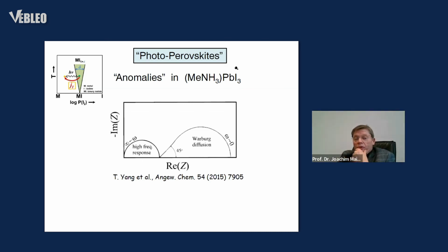Imagine you have such a material and you measure it with a DC current or AC, between 2 electrodes that naturally block the iodine ions. They block it. So what happens is you accumulate the iodine ions on one side, you deplete them on the other side, so you go through that phase width that we have discussed. Now, position-wise, from the left to the right electrode,